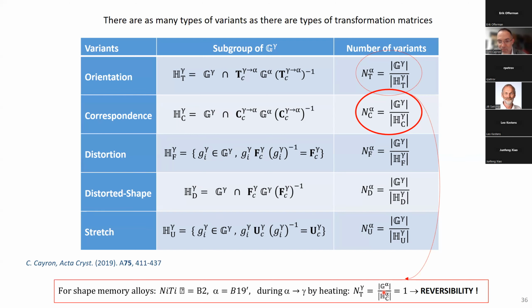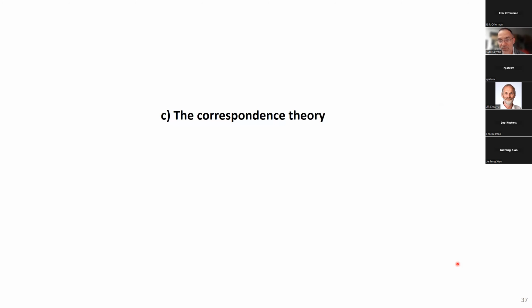And okay, we can even explain the reversibility, for example, in shape memory alloys, because if we look at the number of correspondence variants by the inverse transformation, since the symmetries that are common between the daughter phase and the parent phase, the subgroup of common symmetries, they are the same. It's a monoclinic phase. I will not detail, but you can prove that by the reverse transformation, we have only one variant. We have necessarily a reversible transformation. When we have a group-subgroup relationship between the parent phase and the daughter phase, we have a reversibility that is obtained when you reverse the transformation.